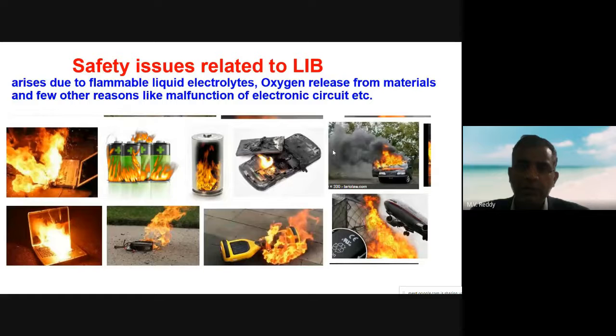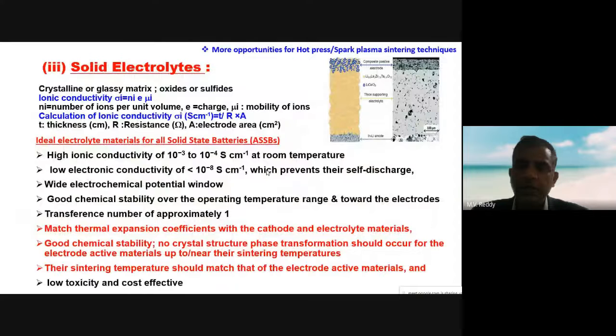So now I'm going to explain the reason why recently another approach is the solid electrolyte, which is mixed with some ceramic membranes, either oxide or sulfide based electrolyte, mixed with cathode and pressed, by hot press or hot press sintering, and we have to go to slightly higher temperature. The problem here is that if you want to prepare something like an A4 sheet roll to roll, these ceramic membranes are difficult at large scale.